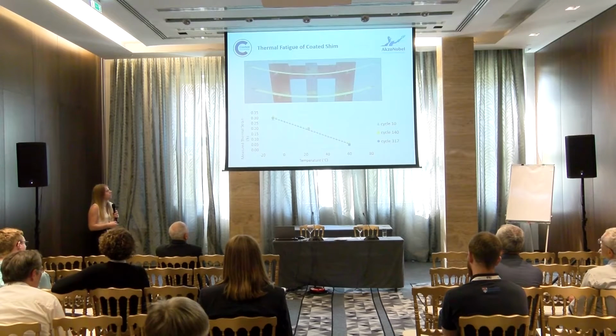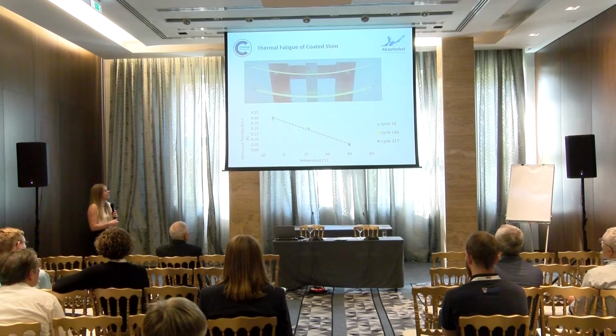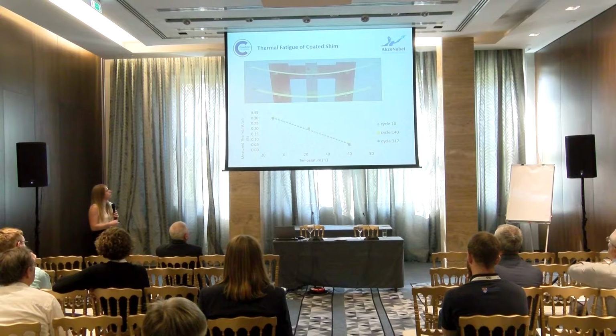As the coating was heated from 23 to 60 degrees, the coating would expand, the shim would straighten, and strains would tend towards zero. As the coating was then cooled from 60 to minus 10 degrees C, and the coating began to contract, we would see an increase in thermal strain, with the largest strains being at minus 10 degrees C, which is, of course, when the material has got its lowest strain to failure.